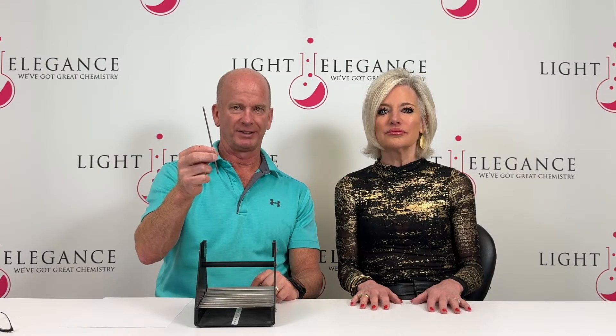Once you have all this information gathered, we write it down and record it. A lot of times when you have a flexible nail, you want to use a flexible gel on top of that flexible nail. Jimmy Gel, being one of our most flexible gels, is one thing you can look at. The Jimmy Gel has a mandrel bend of 1⅛ of an inch — that's very flexible. It also has an elongation where it'll stretch to 50% its original length: if it starts out at 1 inch, it'll stretch up to 1½ inches. That means if the nail is flexible, the gel will bend with that flexible nail and not cause lifting. The more rigid the fingernail, the more rigid the gel you can put on top of it.